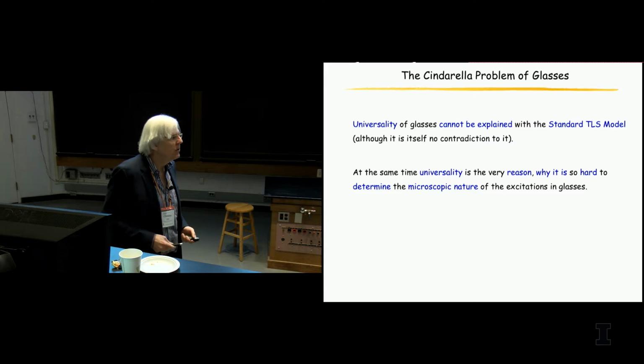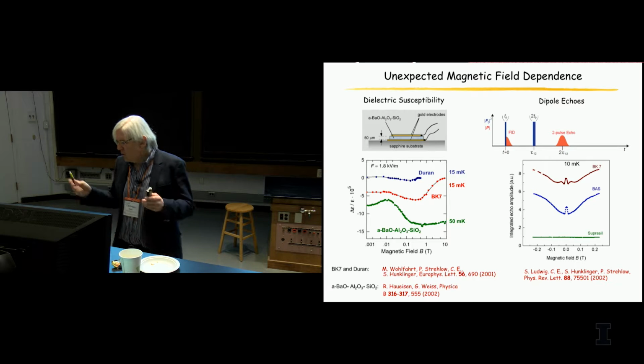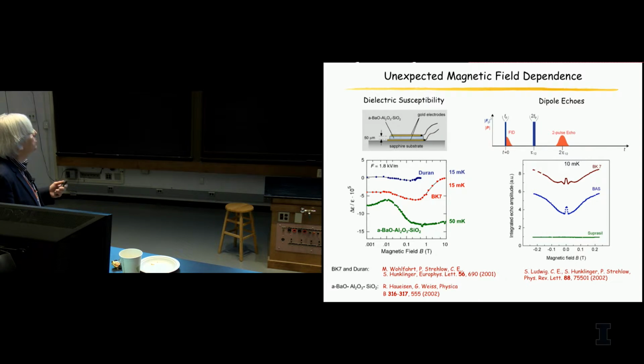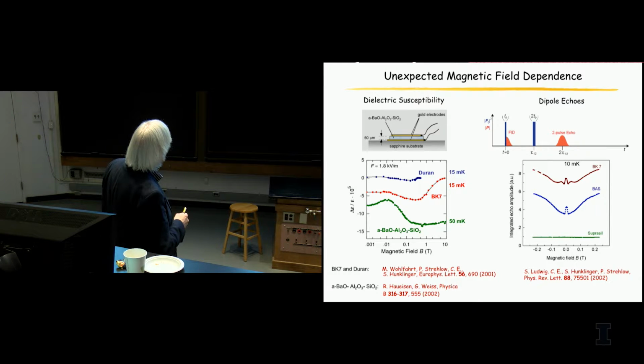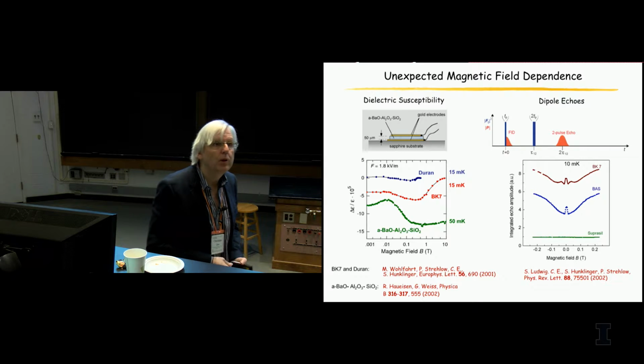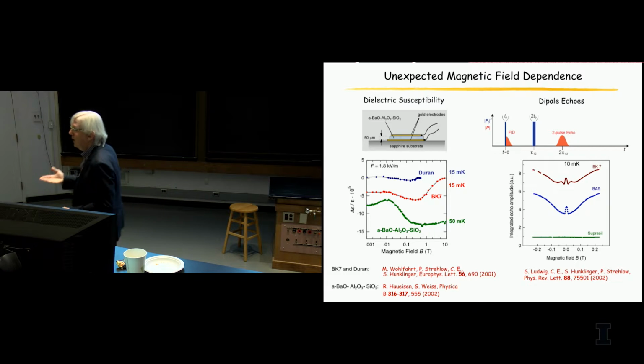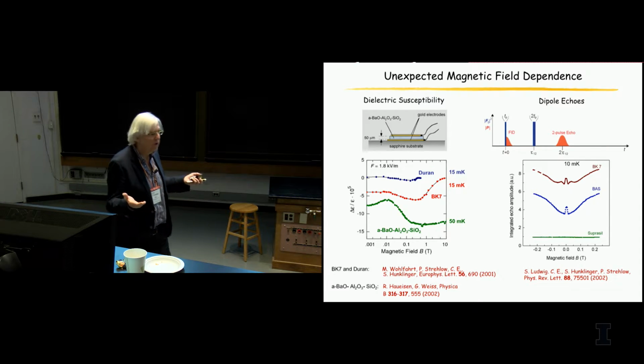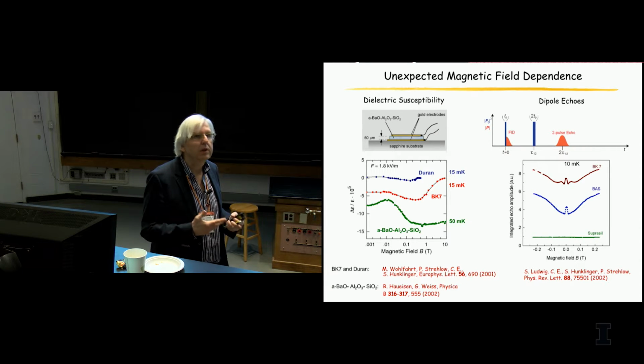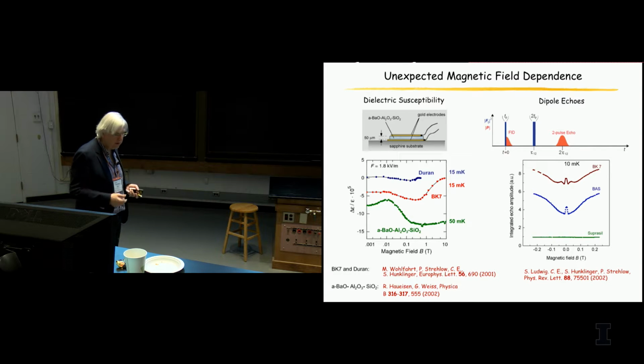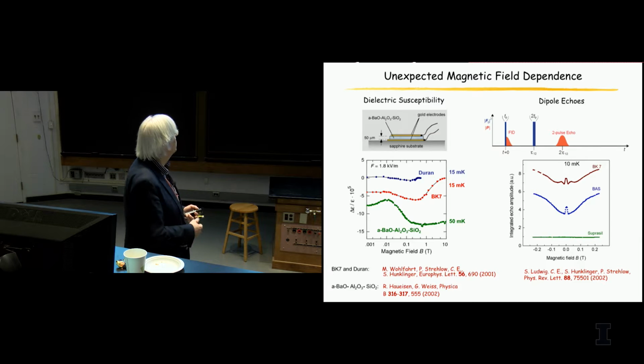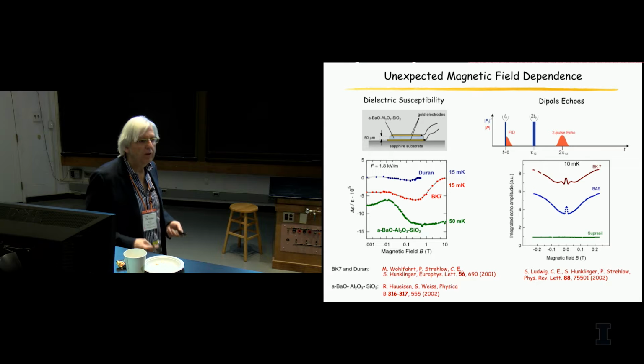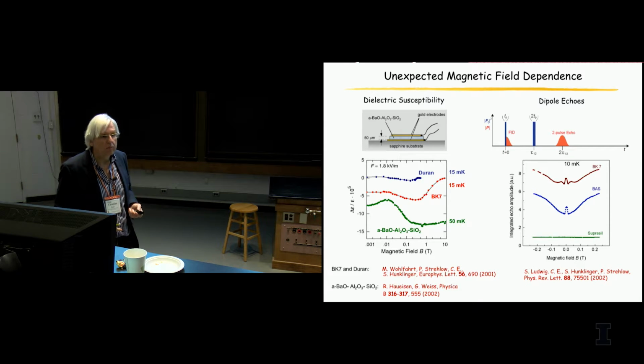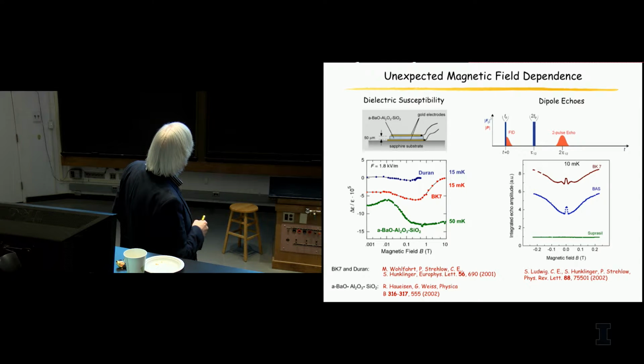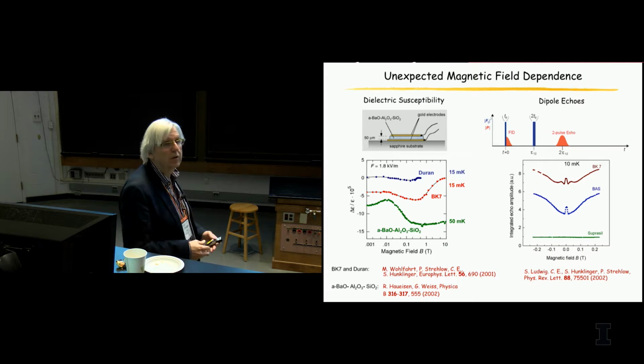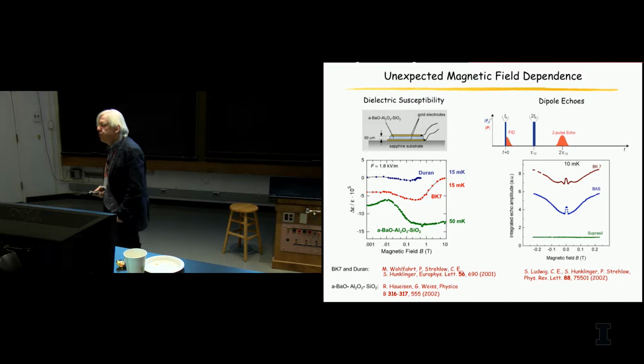Now, let me tell you a little bit about what happened in the last few years. It started already a long time ago with something we didn't understand at all. This is the dielectric susceptibility as a function of magnetic field. Normally, you wouldn't expect any magnetic field dependence in a glass which has no spins. If you have a homogeneous dielectric, in first order, there would not be any magnetic field dependence because the electric field is a polar vector and the magnetic field is an axial vector, and therefore we wouldn't couple in first order. Now, what we see here are measurements of three different glasses as a function of magnetic field, and clearly one sees not only a magnetic field dependence, it was non-monotonic, which was very surprising.